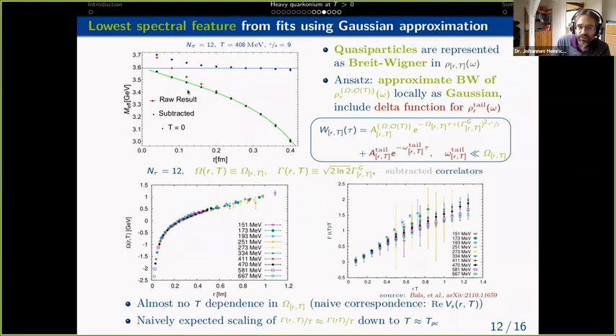The green curve is the fit, and if you repeat this for all temperatures and for all distances, you get the lowest feature of the spectral function that looks like this. You see, for temperatures of 150 to 670 MeV, there is practically no temperature dependence, and within uncertainty it is essentially the zero temperature result for the static energy or for the potential.